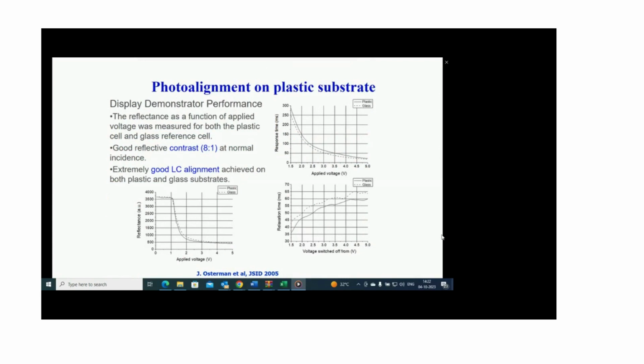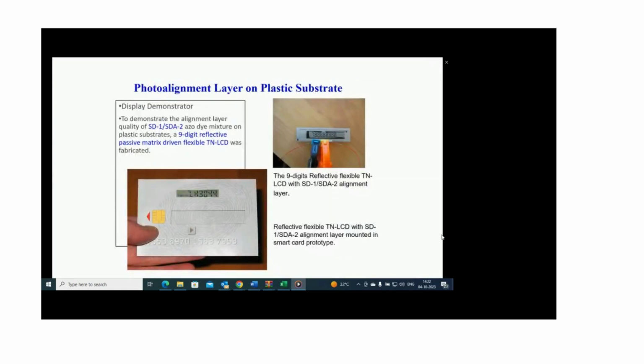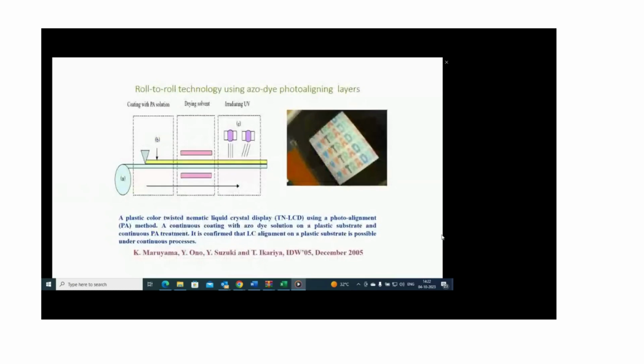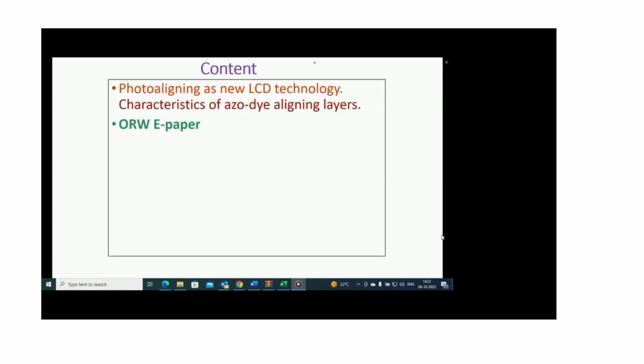Azo dye can effectively align liquid crystals not only on glass, but also on plastic substrates, and key characteristics like reflectance, response time, and relaxation time are almost the same. Moreover, because you don't need the high temperature which is usually used for rubbing materials, you can use many different plastic substrates for alignment of liquid crystal. We demonstrated the photoalignment of liquid crystal on plastic substrates in ATM cards and flexible cards, and we even made a line for roll-to-roll technology using azo dye photoalignment layers together with our collaborators and chemists.